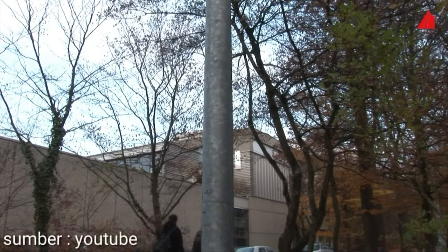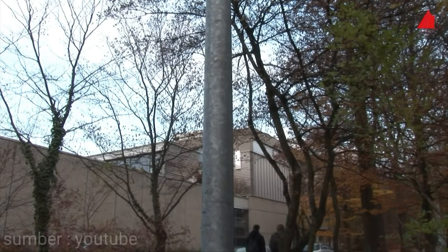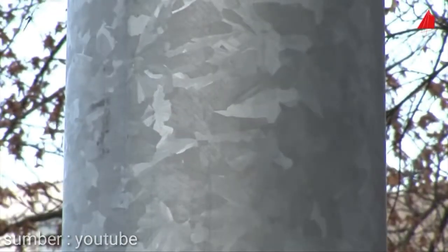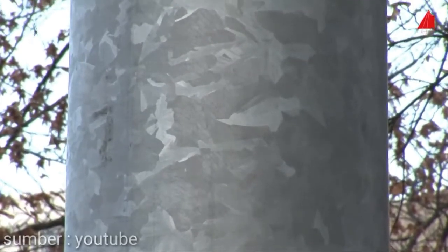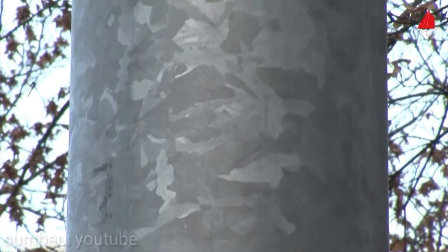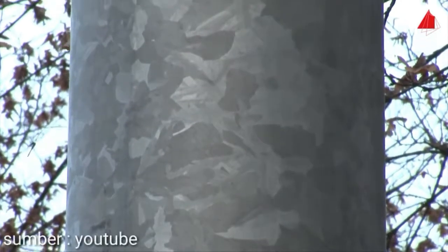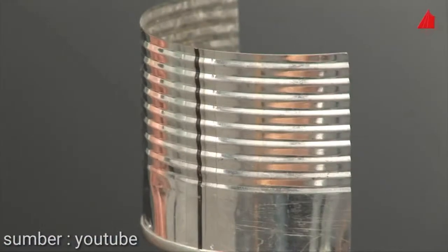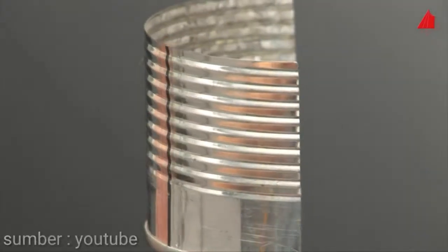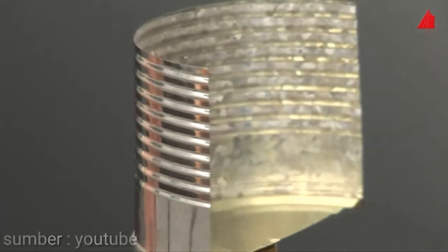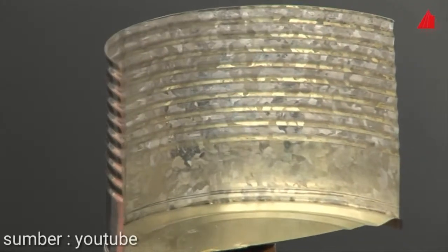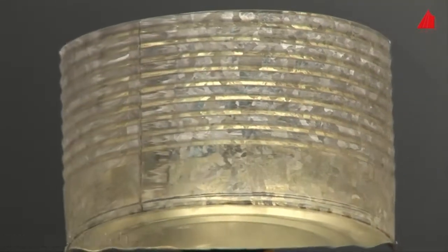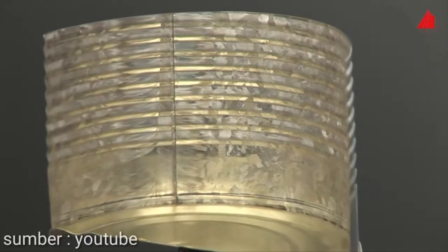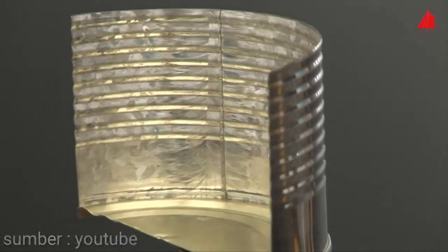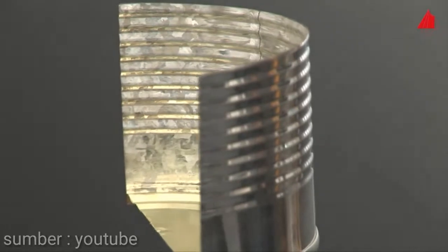Even in everyday life, one meets metallography. At this hot-dip galvanized lamppost, the rainwater has acted as an etchant over the years. The large flat zinc crystals have been structured on the surface and can be recognized as so-called spangle. Even inside of a tin plate steel can, crystals are visible. The fruit acid of pineapples has etched the flat crystals of the tin coating. A natural and unintentional grain contrast etching process has taken place. On the outside, the tin coating is still unchanged and shines like new.